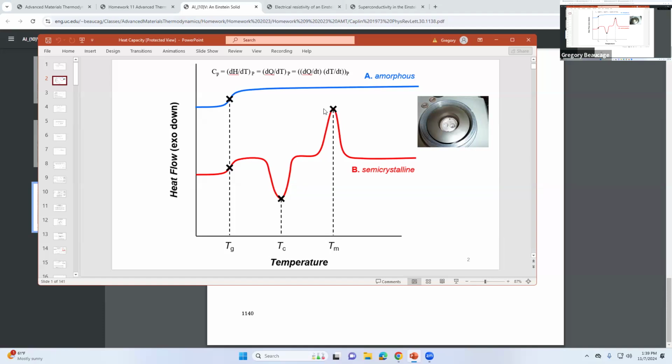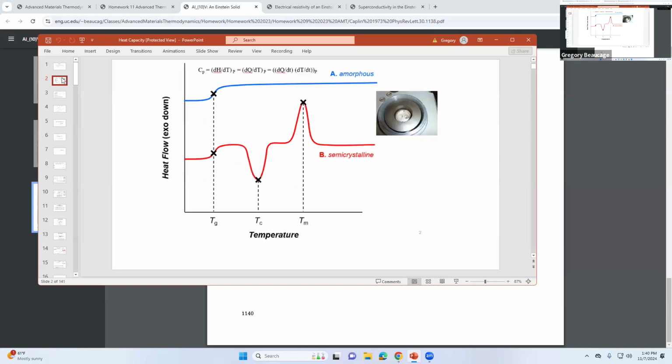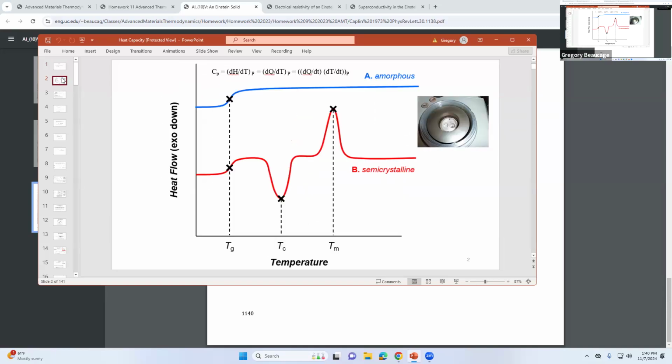But you use indium or some metal to standardize the temperature scale because it's just got a spike and it's just exactly where. So indium and naphthalene, sometimes you use mothballs. They have spikes here, so you can calibrate. So usually you use indium and naphthalene. You have at least 2 points to get the scale right for temperature. And then you also know from the mass of the indium and the naphthalene you put in, you can get this scale right too. So you calibrate the thing with standards before you run it. And that's kind of the workhorse for thermodynamics, actually, for measurements.